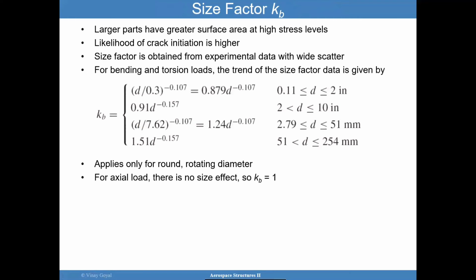So the size factor is important. I discussed this before. Larger parts have a greater surface area at higher stress levels. Likelihood of crack initiation is higher. Size factor is obtained from experimental data with wide scatter. For bending and torsional loads, the trend of the size factor has been found to follow this. This only applies for round rotating diameter. For axial load, there's no size effect, so we'll just take Kb equals 1. But if you have a round rotating diameter, then you have to consider these calculations here.